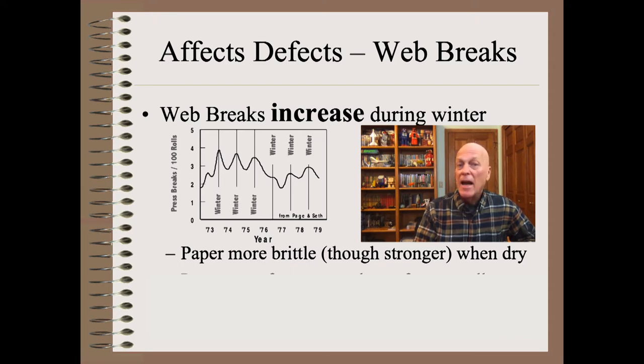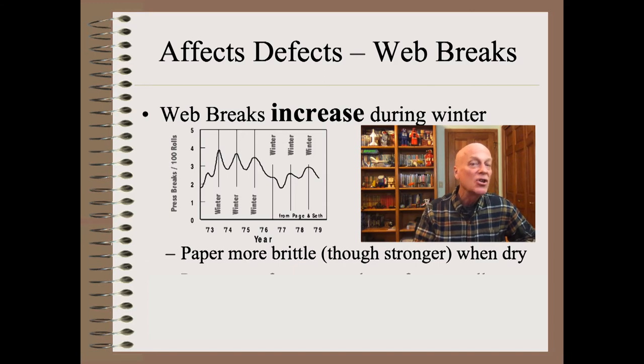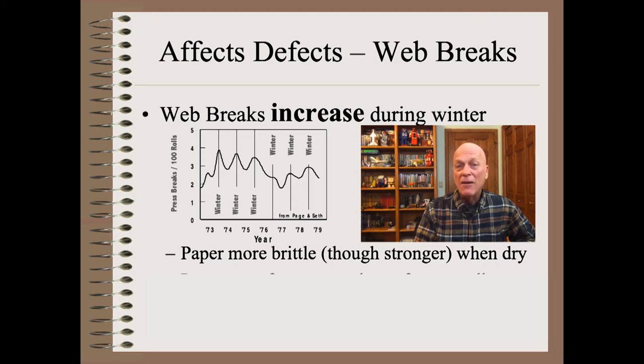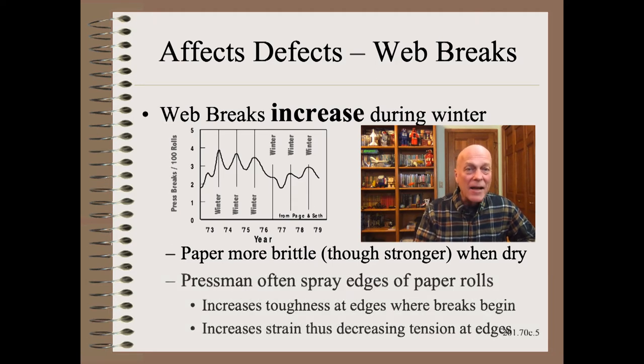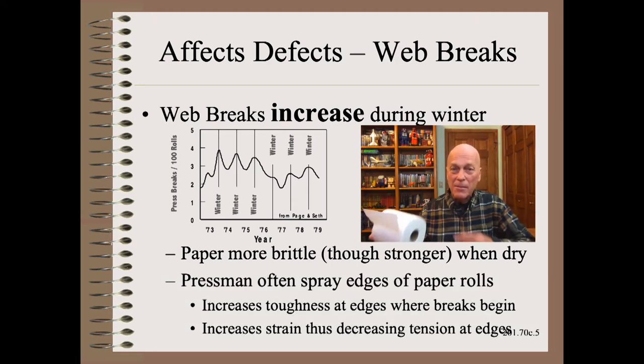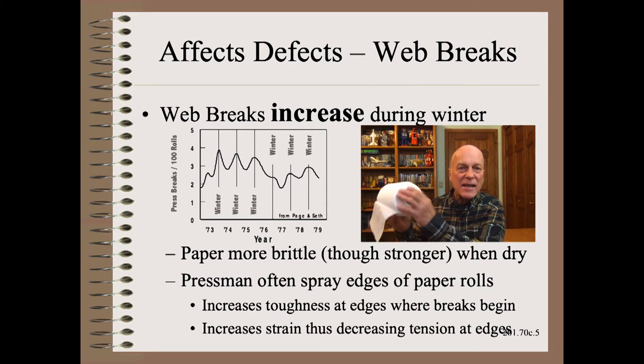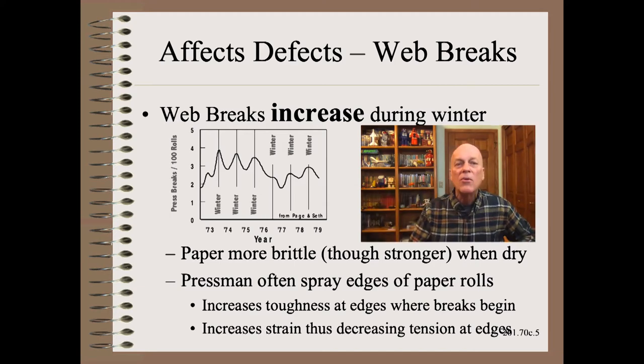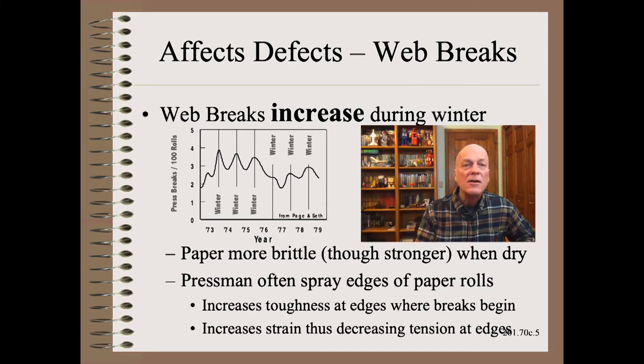This knowledge changed the printing industry in many ways. Paper mills and printers alike started to think about specifying and controlling environmental moisture as well as the paper moisture. If they could not afford that, the printing pressman would sometimes lightly spray the edges of the wound rolls and let them sit for a few minutes before they were run.